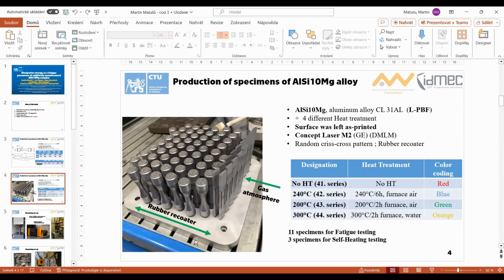The first series was without the post-processing. The second series was post-processed by recommended values by the manufacturer of this powder. The third and fourth temperature heat treatments were just an interesting part for this research, because the 300 degrees should decompose the silicon bonding in the structure and make the structure more ductile compared to the non-heat treated specimen.